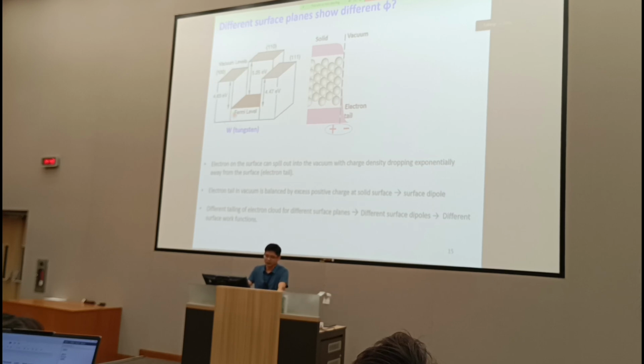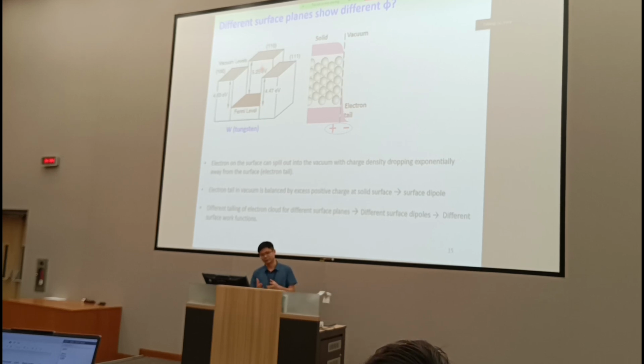This basically illustrates that. Imagine you have nanoparticles, and nanoparticles have three dimensions, terminated by different facets. Like cubic nanoparticles, they can have 1,0,0, 1,1,0. But if you look locally, when you take electrons from certain phases, the work function can change quite dramatically, from 4.63 to 5.23. So if you use different types of facets to facilitate charge transfer between the adsorbates, all these different work functions matter.